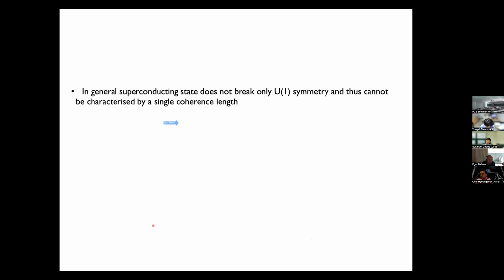Okay, and on the one hand, that seemed to be quite a generic classification of superconductors, because it's an energy argument. The interface energy could be either positive or negative, and if you start generalizing models to more complicated ones, you still would get either positive energy interfaces or negative energy interfaces. Even with, let's say, a multi-component Ginzburg-Landau model, that seemingly would still furnish a very good classification. However, I will be arguing that it's not so, and there is one important aspect which is missing in the original Ginzburg-Landau argument.